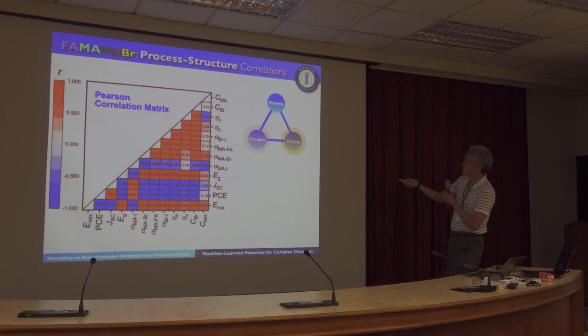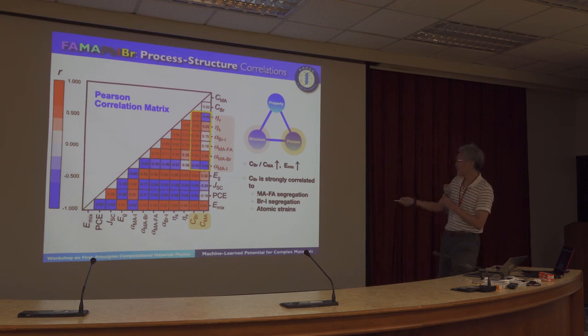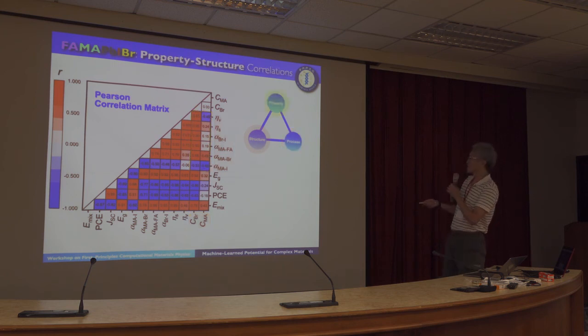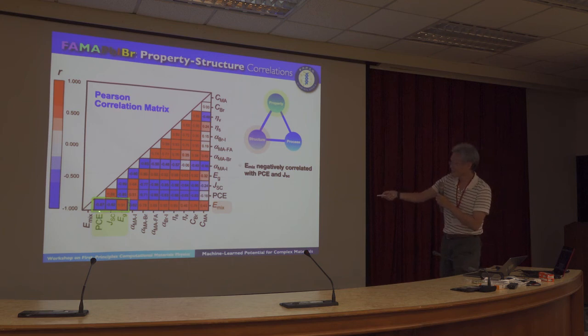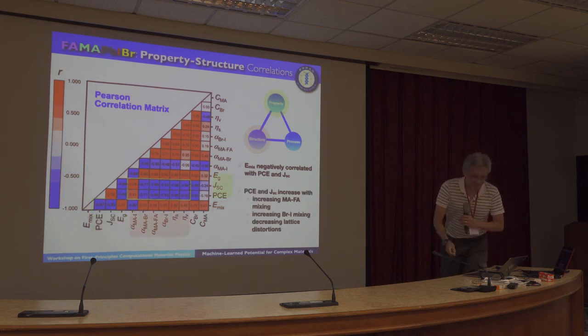And about the process and the structure, we can find that bromine concentration has strong correlations with mixing energies. We can also find that bromine concentration is strongly correlated to the segregation of MA and FA, and bromine and iodine, and also strains. So we know that bromine concentration is very important. And finally, let's look at the property and structures. So we know that the mixing energy is negatively correlated to conversion efficiency and short circuit current density. We also notice that once again the conversion efficiency and short circuit currents are inversely correlated with phase segregation.